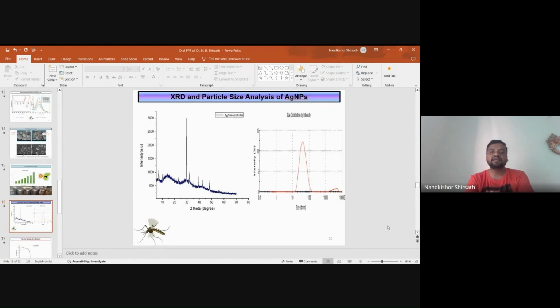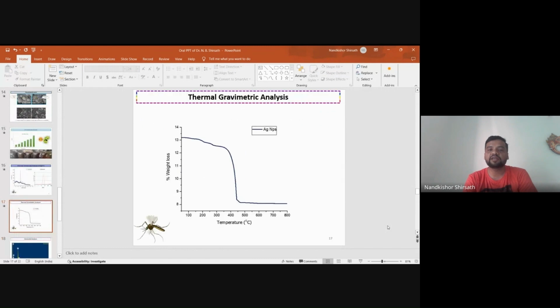These are the XRD analysis of the synthesized material. As we can see, the particle size is near about 70 nanometer, which was confirmed with the help of XRD and the particle size analysis. These are the thermal gravimetric analysis. As we already discussed, our particle is stable up to around 450 degrees Celsius, so it has good thermal stability.